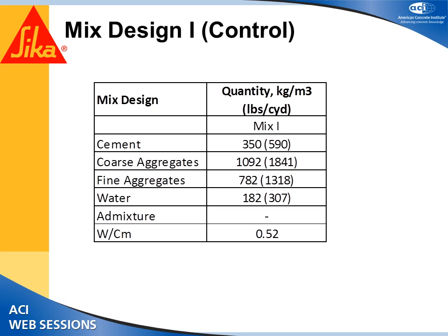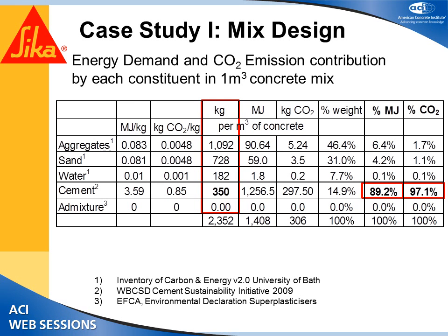So this was mix design number 1, which has a cement content of 590 pounds of cement and a water cement ratio of 0.52. For this mix design, it was calculated how much energy was utilized and how much carbon dioxide was emitted for each of the constituents. This is the mix design in kg per meter cube, and these are the ingredients. And if you look at the percent energy consumption of all the materials, you can see that it was highest for the cement, and also the carbon dioxide emission was the highest for the cement.